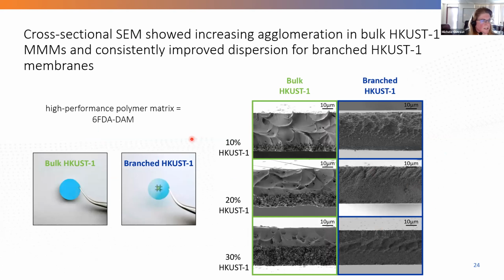When you combine these materials with a polymer matrix, in this case 6-FDA DAM, you notice the bulk materials produce an opaque film, whereas the branched nanoparticles produce a more transparent film. And when you look at the cross-sectional interface of these materials, you can see that the bulk materials in general are agglomerating and basically settling out when the film is cast. That leads to poorer performance of the overall membrane, and it also leads to these being opaque materials. Whereas the branched materials are much more uniformly dispersed throughout the entire membrane, really making these pretty effective mixed matrix membranes.